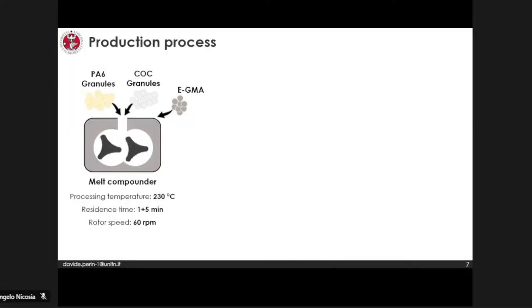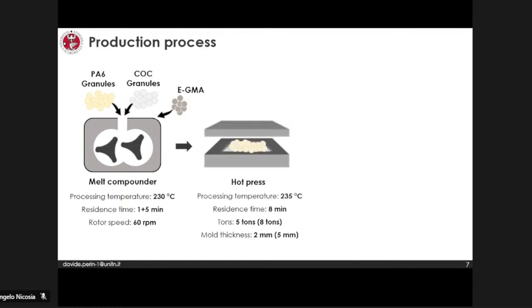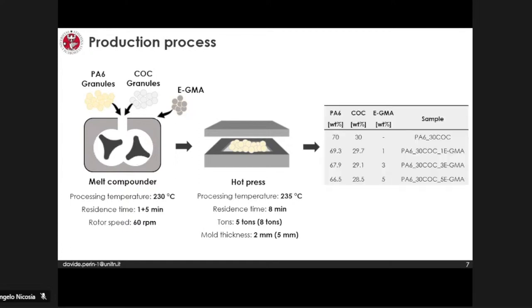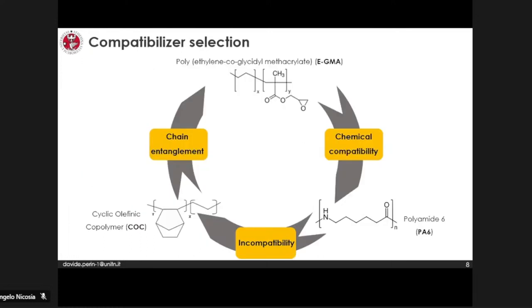As a matrix, I selected polyamide 6, which is one of the best technopolymers. As a healing agent, I selected cycloolefinic copolymer, COC, and as a compatibilizer, I selected polyethylene-co-glycidyl methacrylate, aka EGMA for friends. I blended everything inside my compounder, then I granulated and hot pressed to produce the slabs for further characterization, and in this way I obtained several slabs with a fixed amount of COC and increasing amount of the compatibilizer.